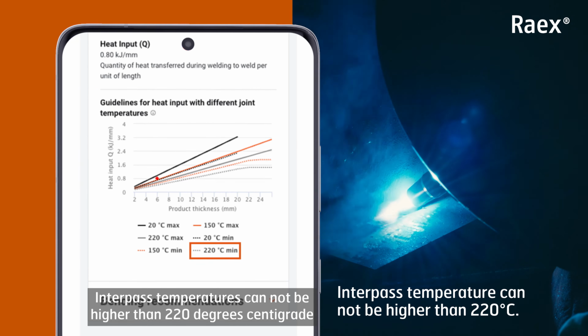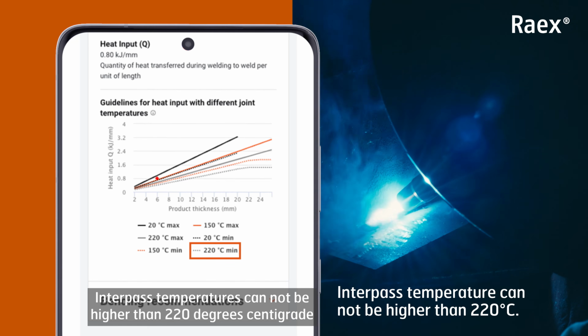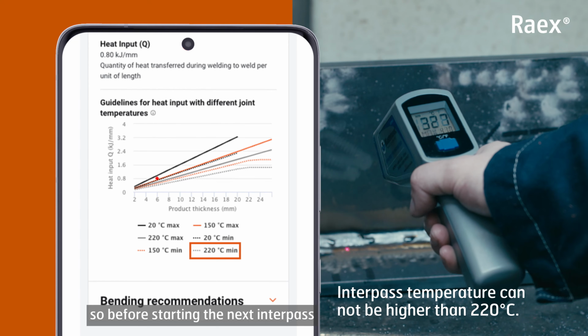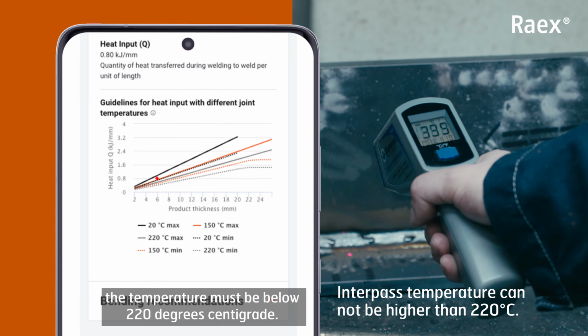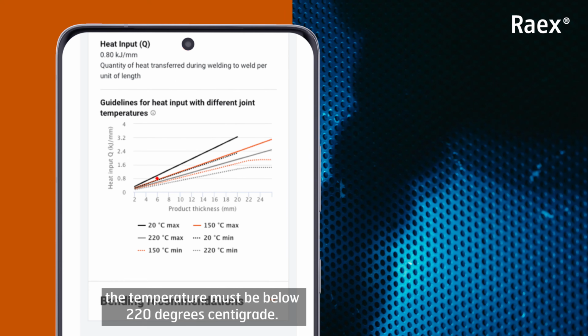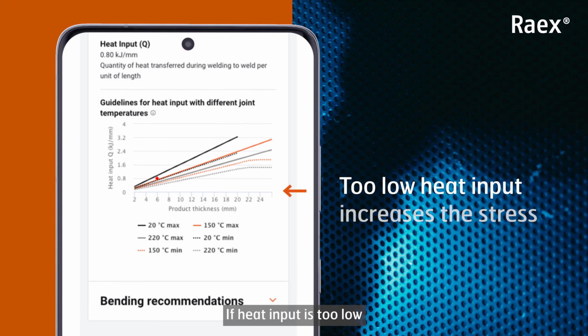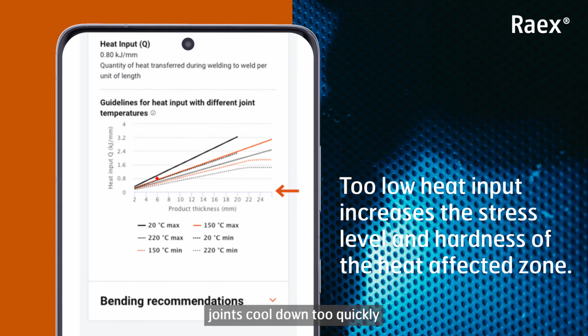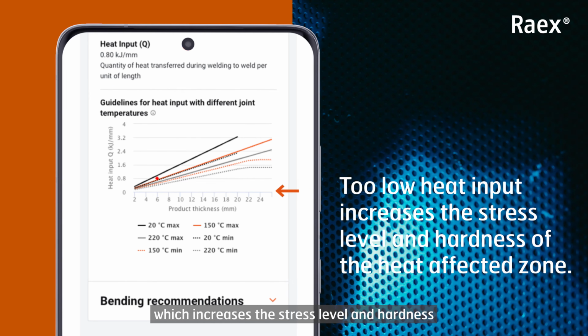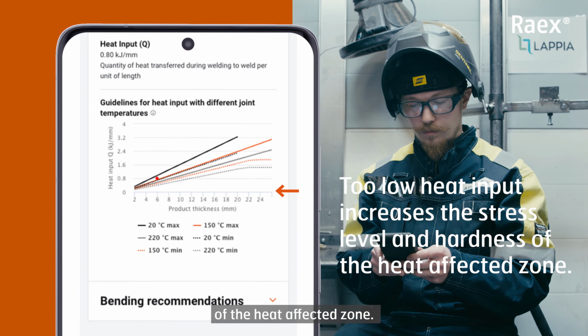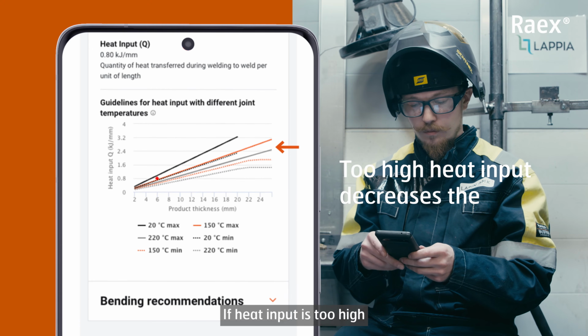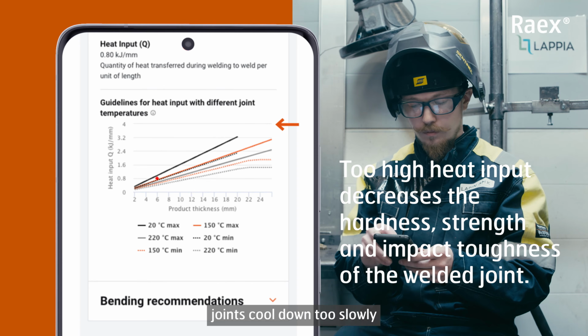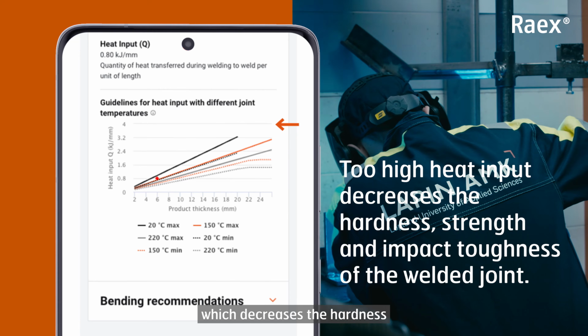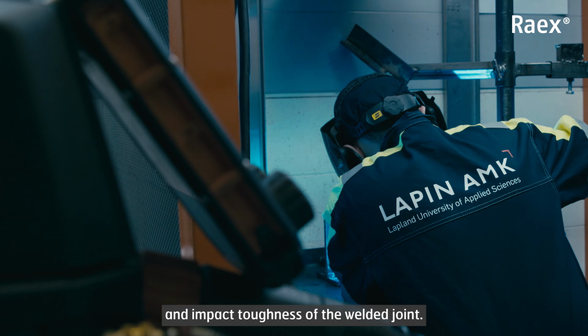Interpass temperatures cannot be higher than 220 degrees centigrade, so before starting the next interpass, the temperature must be below 220 degrees centigrade. If heat input is too low, joints cool down too quickly, which increases the stress level and hardness of the heat-affected zone. If heat input is too high, joints cool down too slowly, which decreases the hardness, strength, and impact toughness of the welded joint.